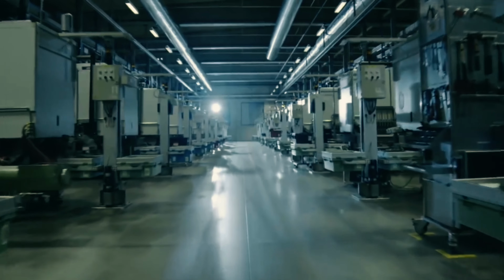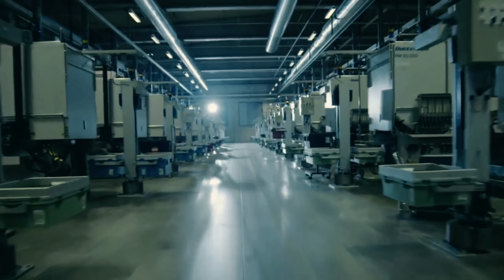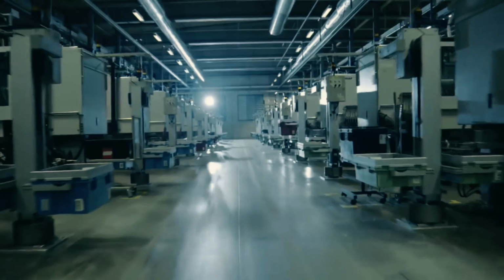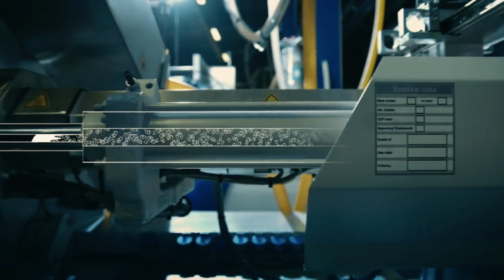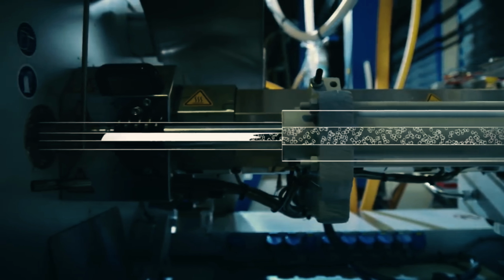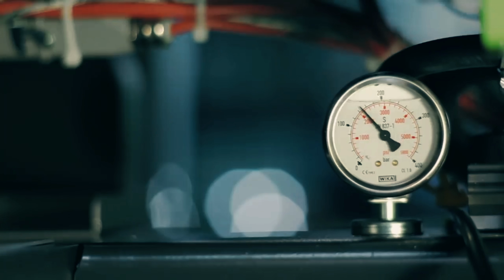The pellets are fed into a hopper and melted at temperatures around 450 degrees Fahrenheit. From there, the molten plastic is forced under enormous pressure, sometimes tons per square inch, into a steel mold engraved with the exact shape of the toy piece, down to fractions of a millimeter.